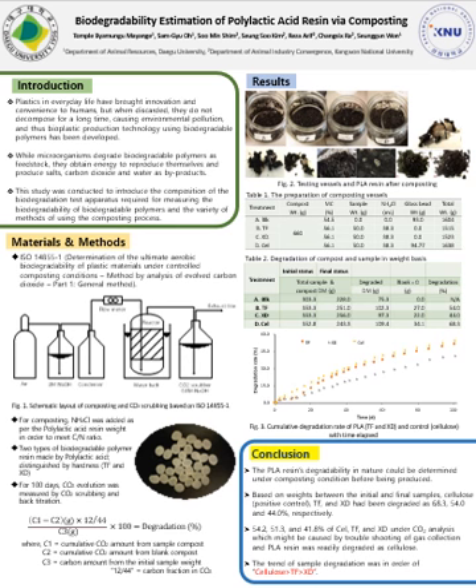Then to reach our goal, first we used the method ISO 14855-1, which is the method for the determination of the ultimate aerobic biodegradability of plastics based on organic compound under controlled composting conditions by measuring the amount of carbon dioxide evolved and the degree of disintegration of the plastic at the end of the experiment. And this Figure 1 shows the schematic layout of composting and the CO2 scrubbing based on this method.